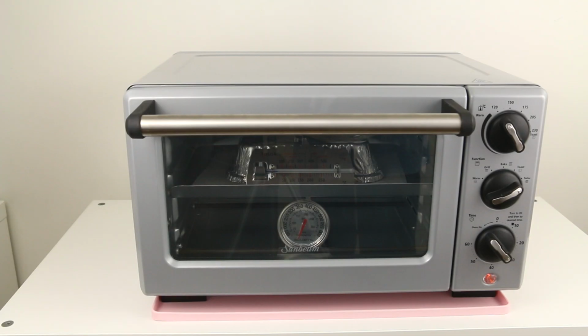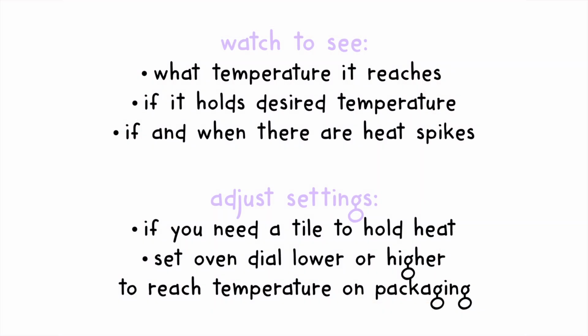First, preheat the oven and baking surface for about 20 minutes with the thermometer inside, just so that it comes up to the temperature on the clay packaging. If you're using a tile inside your oven, it takes longer to heat up. Then watch the thermometer through the door without any clay inside to see what temperature it reaches, if it holds heat, if and when there are any heat spikes, etc. Then just adjust the settings to get the right temperature on the thermometer, like if you need a tile to hold in the heat, or set the dial lower or higher to reach the temperature on the packaging, etc.